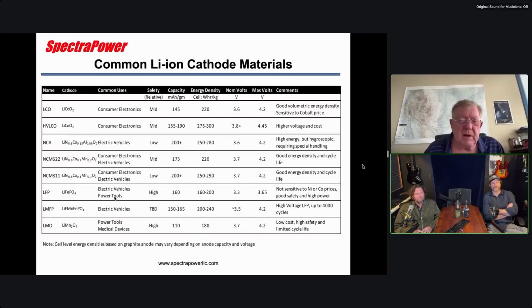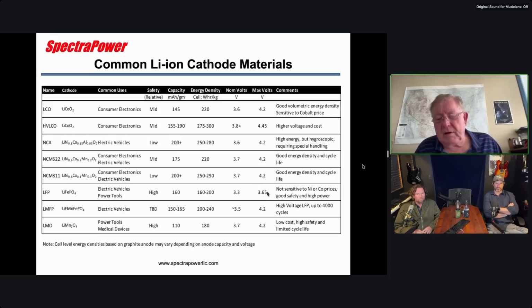And then there's a couple more. LMFP is interesting because it's an effort to improve the energy density in iron phosphate by raising the voltage. So iron phosphate has typically a lower voltage, this 3.65 is the max charge for iron phosphate. Typical discharge voltage is around 3.25, 3.3. And if you put in manganese, you can get up to 4.2. And this bumps your energy density up to where it's very competitive.